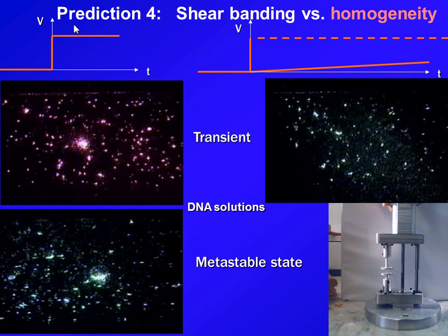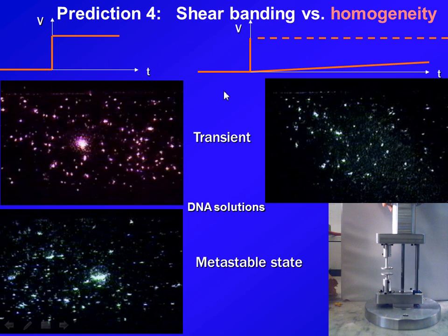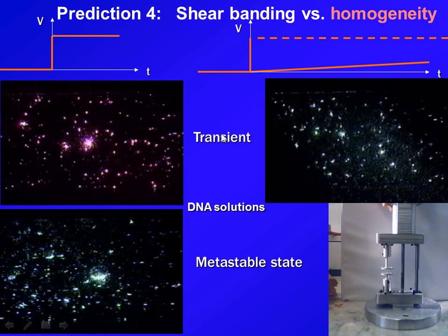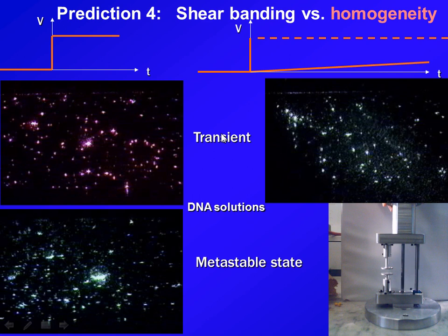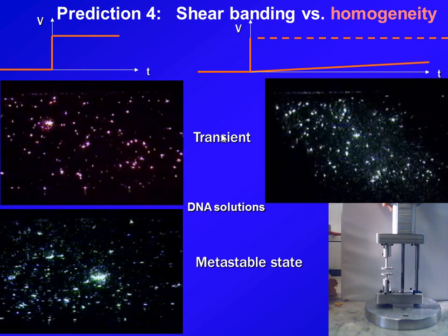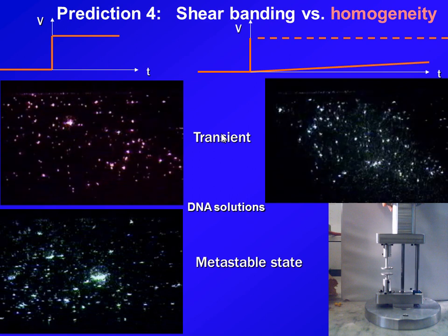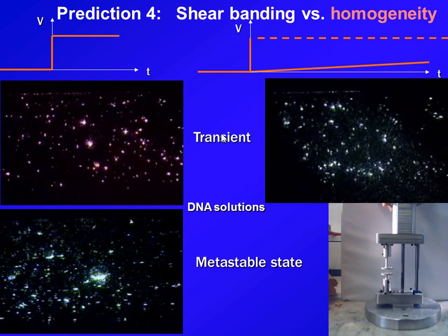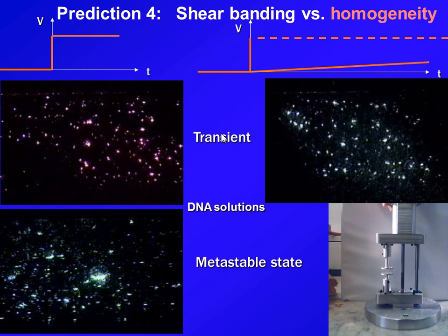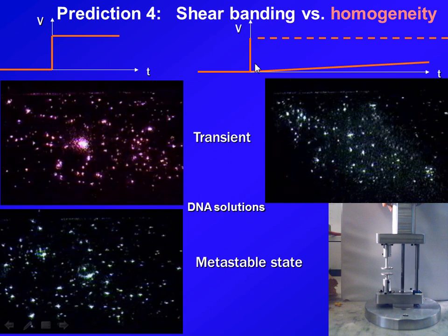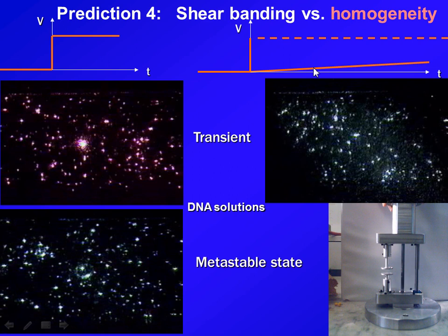That's the reality. Then we propose that what if I slowly move my upper velocity, eventually to the same speed, but very slowly. Takes 8 hours, it turns out. So during this time, it's much longer than tau. So we are happy, we make sure the molecules, the rice noodles are happy, given them enough time to diffuse around. It turns out then you avoided shear banding. So this is the steady state if you abruptly apply the shear versus you infinitely slowly apply the shear.